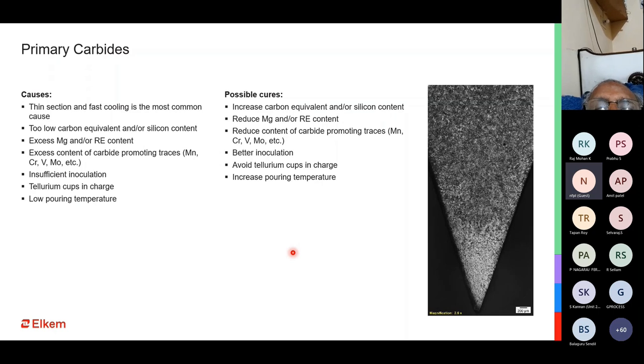Possible cures. We have to make sure that our carbon equivalent and our silicon are selected in the most suitable manner, such that it is good enough to give you graphite. We have to have a control on magnesium and other trace elements. We have to ensure that our metal has a very good nucleating potential, which can come from better inoculants, which can come from better preconditioning, which can come from a very good base iron, for example use of pig irons or good graphitizers, or having a control on the quality of other charge materials that we have.